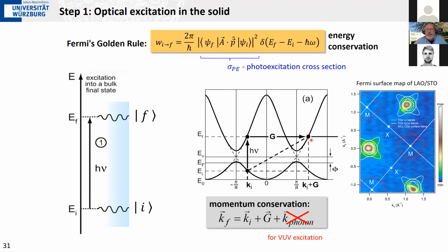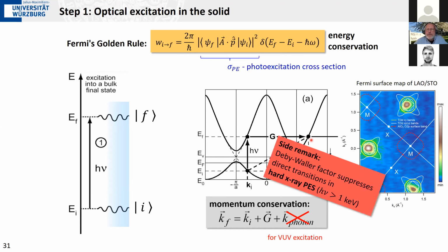One caveat at this point here. When I say we have these direct transitions, we have to take into account something like a Debye-Waller factor, something that you also know from X-ray diffraction. When you have a finite temperature, the phonons in your system will, by their very existence, destroy the periodicity of your crystal structure, and transfer spectral weight from your Bragg peaks to incoherent scattering between the Bragg peaks.